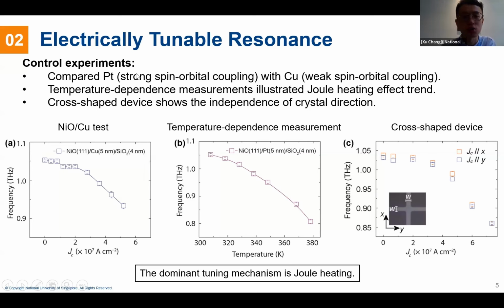Platinum is known to have strong spin-orbit coupling, but copper is known for weak spin-orbit coupling. The nickel oxide copper device test also shows monotonically decreasing spectra, showing exactly the same trend as the previously shown data of the platinum device. So this has eliminated the possibility of SOT tuning. Then we conducted a temperature-dependent measurement. When we increase the temperature, we can see the frequency is actually decreasing. This gives us a hint that the redshift of the resonance frequency is actually caused by Joule heating.